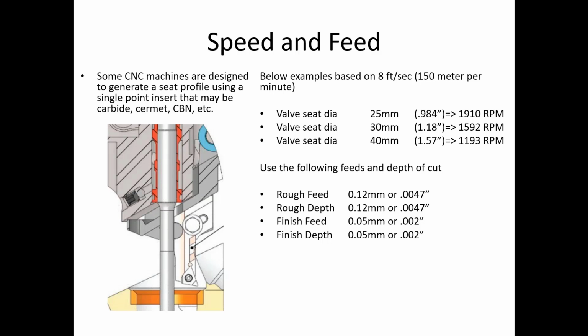They actually have some profiles where you would machine on the bottom edge of the insert for your roughing, and then you travel from the inside diameter to the outside diameter, so that you're using the opposite edge of the insert for the finishing process. So it almost is like you have 2 separate cutting surfaces, and it's only cutting about 5 thousandths of material as opposed to, again, 300 to 400 thou. So that's some of the technologies out there today.